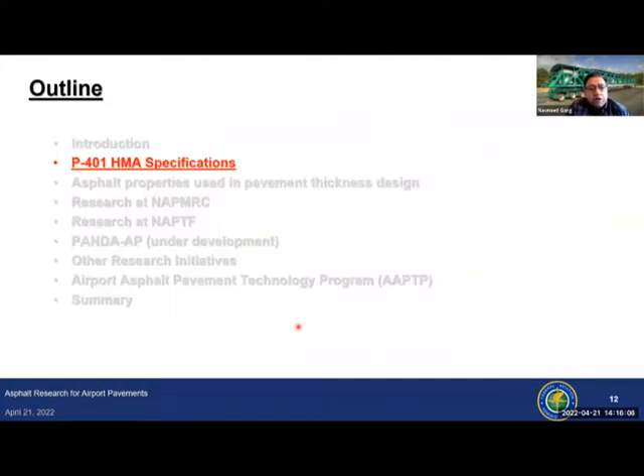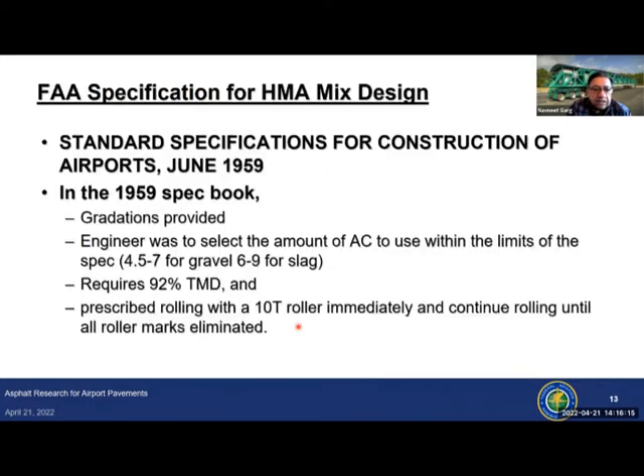So next I'll talk about P401 hot mix asphalt specifications. P401 is a specification in FAA advisory circular for hot mix asphalt. So the first advisory circular that talked about construction of airports was issued in June of 1959. And in this specification book, they provided gradations that were to be used for asphalt mix design. Engineer was to select the amount of asphalt content depending on whether it was gravel or slag. And you needed minimum of 92% theoretical max density.